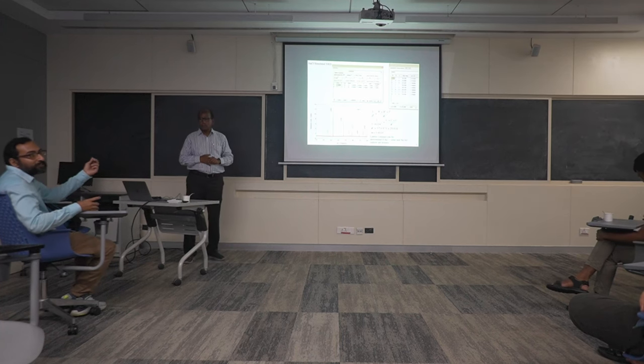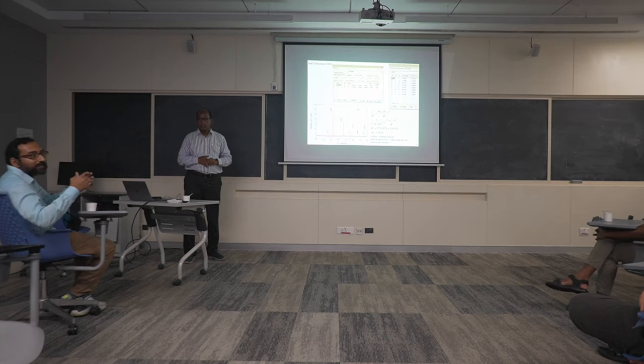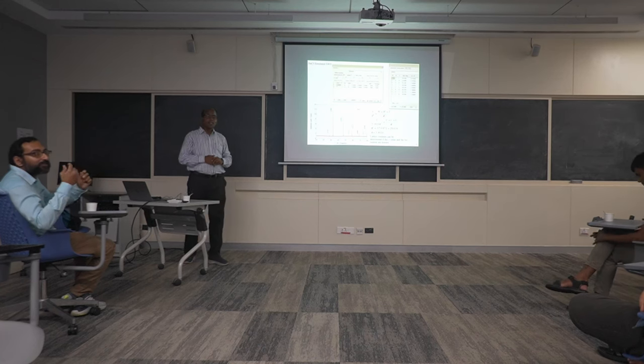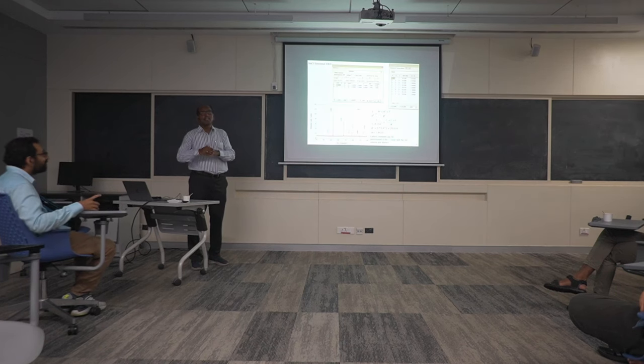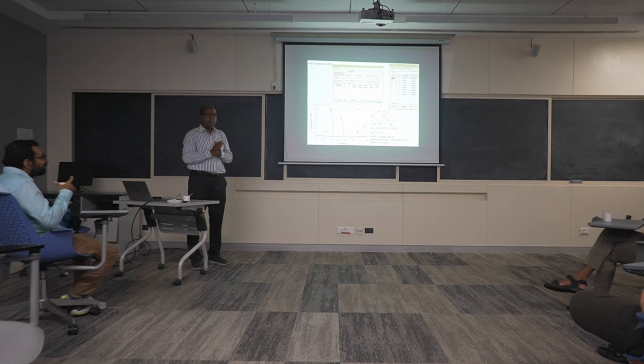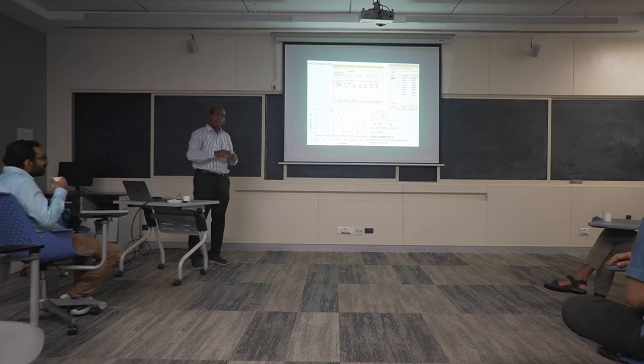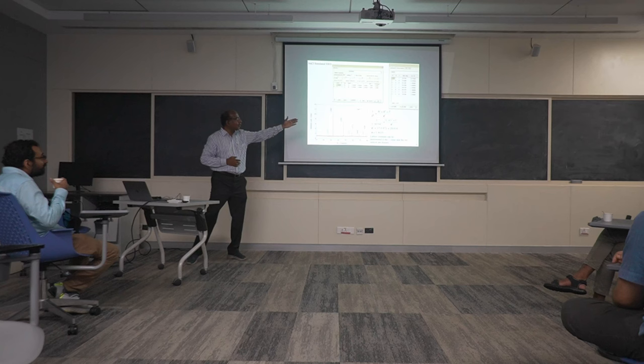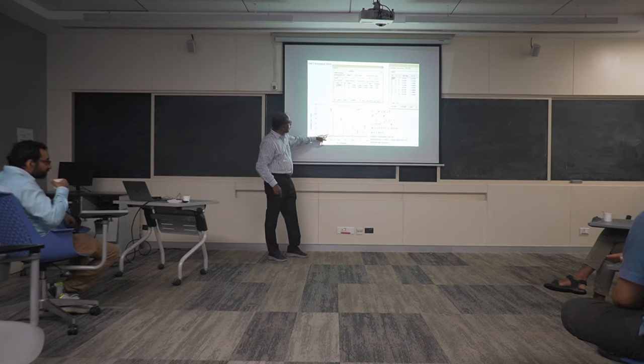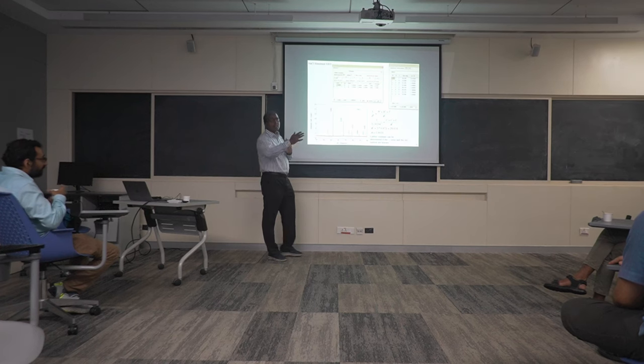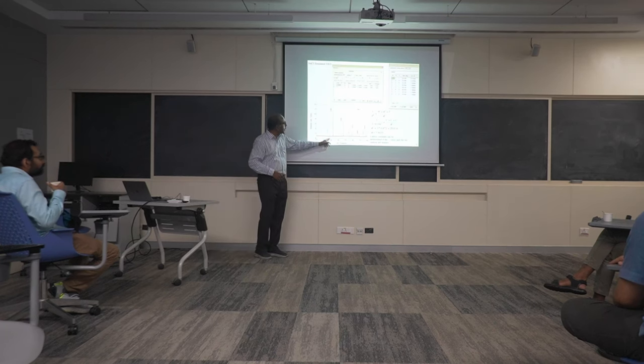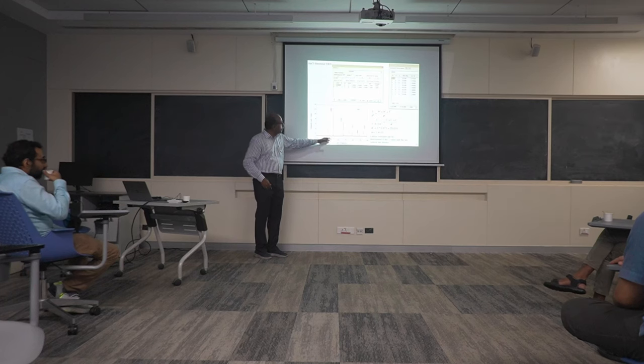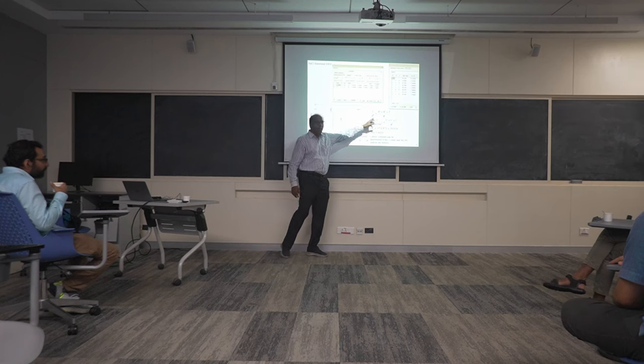We compare experimental data with theoretical models through Rietveld refinement, which tells us how pure the material is and whether there are one or multiple phases. For research purposes this refinement is very useful. For a basic experiment, you just index the peaks — this peak is (1,1,1), this is (2,0,0) — and if you have made some doping, the (1,1,1) peak may shift from 29° to 30° 2-theta; you calculate D for that angle and estimate the lattice constant. The lattice constant changes reflect chemical pressure from substituting atoms of different ionic radii.